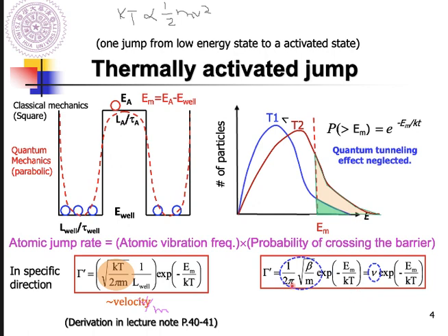The vibration frequency result is shown here, equal to 1 divided by 2 pi times the square root of beta divided by m. Beta here is a force constant, and in materials, we consider this related to the bond strength between atoms. And m is a mass, but here it is a reduced mass related to the type of atoms we're talking about.